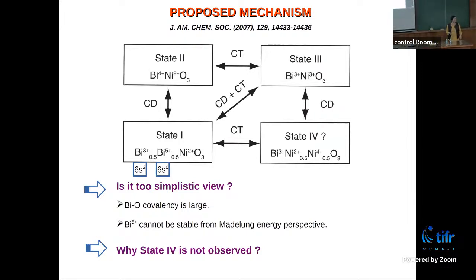They said that the bismuth is not in a 3+ state. Bismuth is in 4+, nickel 2+, and O3. That's the situation. And since bismuth doesn't like 4+, bismuth charge disproportionates to 3+ and 5+. And by putting pressure, what happens is a charge transfer between bismuth and nickel. So instead of bismuth 4+, nickel 2+, it becomes bismuth 3+ and nickel 3+.